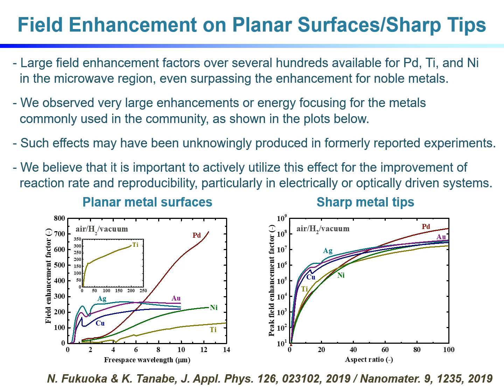For sharp metal tips, depending on the aspect ratio of the virtual spheroidal structure, we observed very large enhancements, or an energy focusing effect like an antenna. We believe that it is important to actively utilize such plasmonic field enhancement effects for the improvement of reaction rate and reproducibility, particularly in electrically or optically driven systems.